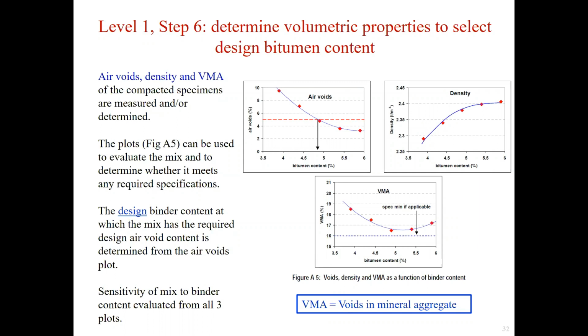After we conduct tests on samples of 5 different bitumen contents, we are able to get a relationship plot of air void density and VMA (voids in mineral aggregate) of the compacted samples against bitumen content. These could be used to evaluate whether the mix meets any required specifications. If the mix has the required air void content, the binder content could be determined from the plot.